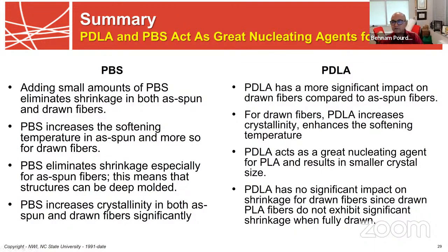And when you look at the addition of the PDLA, it's really more significant for fully drawn fibers and increases the crystallinity, but you have lots of smaller crystals. It also enhances your softening temperature significantly, very similar to PBS. And then it really doesn't impact the shrinkage as much. It's for fully drawn fibers, but you have two pathways that we could use without really resorting to anything else. And what's also really interesting is that you don't even have to pre-compound these. So you could essentially feed these polymers at the throat of the extruder without compounding them. And the extruders are typically long enough that you get enough mixing, and that reduces the challenge of having to pre-compound these and eliminates some extra costs.